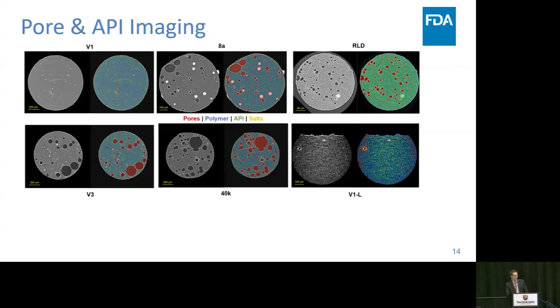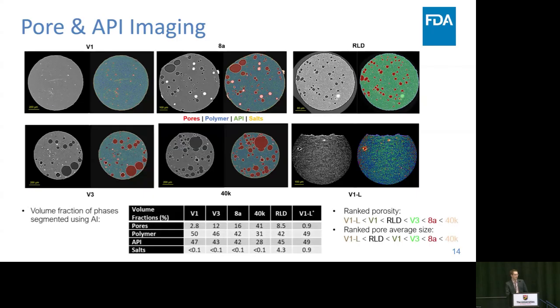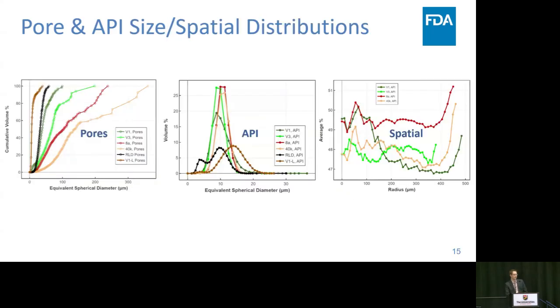And also looking at the pores, we can do XRM using our micro CT system. So this is using X-ray imaging to look at the pore and the API distribution within the inserts. So this is very useful for telling the volume fraction of the pores, polymers, and API. And we can rank the porosity and the pore average size. And from there, we can also come up with the size distribution and the spatial distribution of these and compare how they relate to each other.